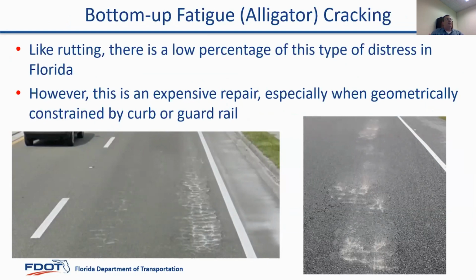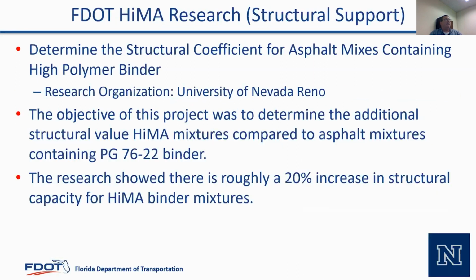Now, you can't just build the pavement up and increase the thickness maybe to help. You've got to go deep and start trading mix for base or doing something else if you're not thick enough. So again, we found that the high polymer binder gives more structural support and helps reduce those bottom-up cracks better. So when we do have issues like this, we look to use the high polymer binder to address the issue. And again, we've got research to back it up. There's the title of the research that was done by the University of Nevada, Reno. Dr. Sabali, Dr. Haj did that research.